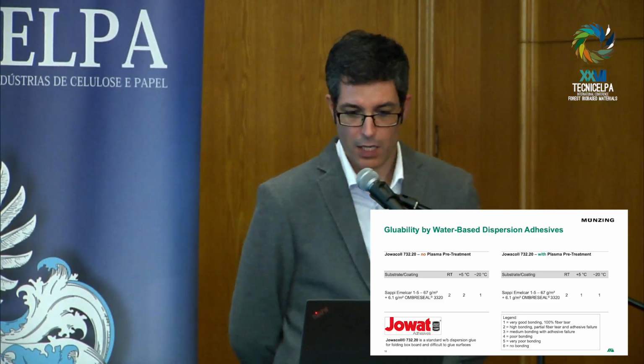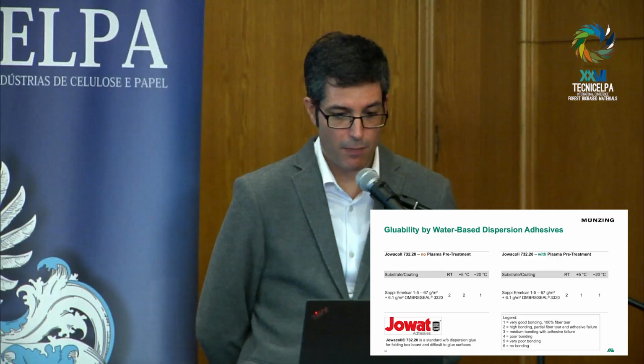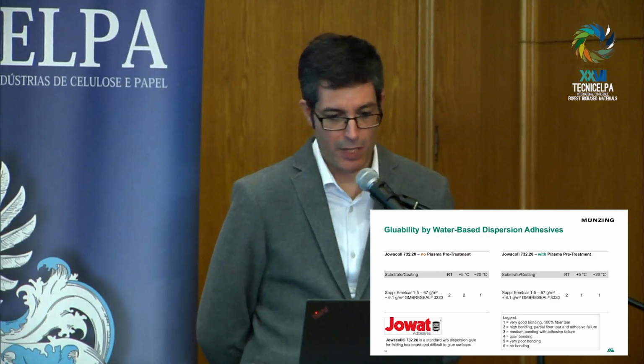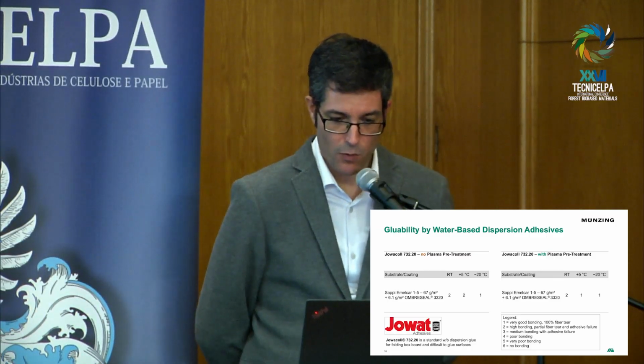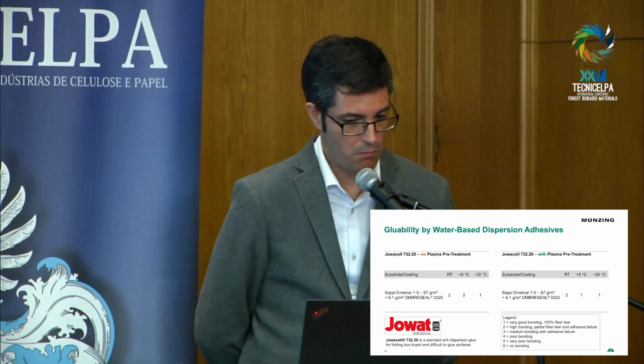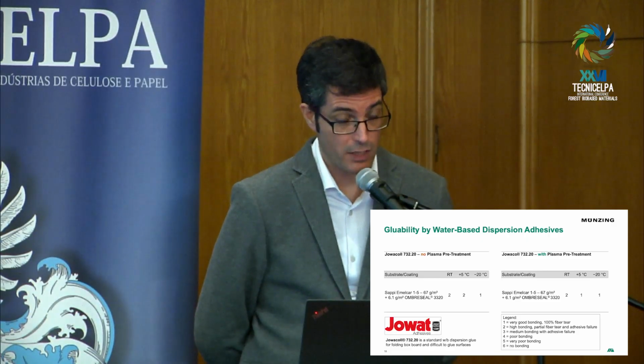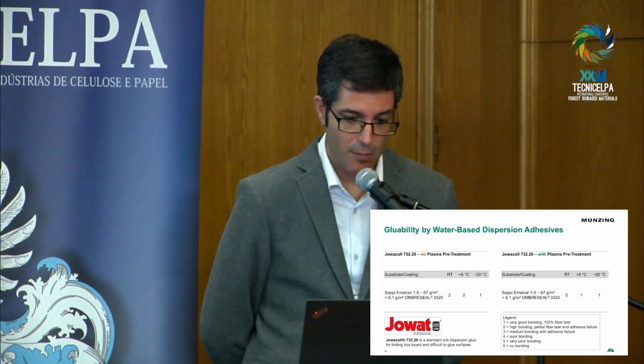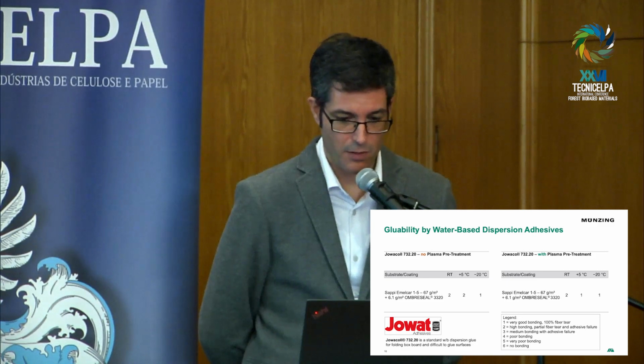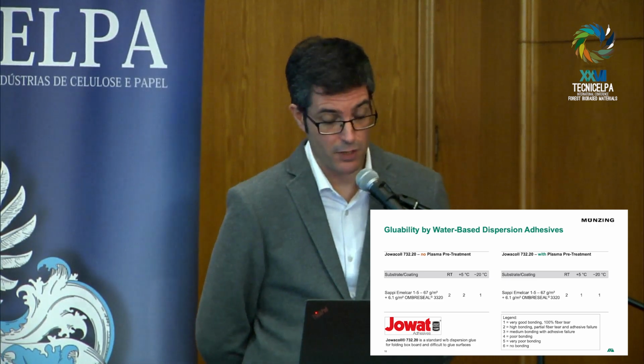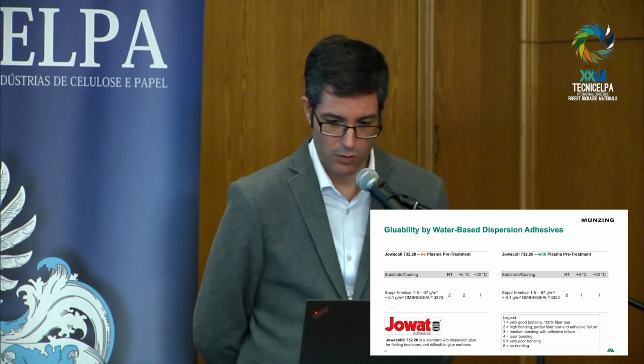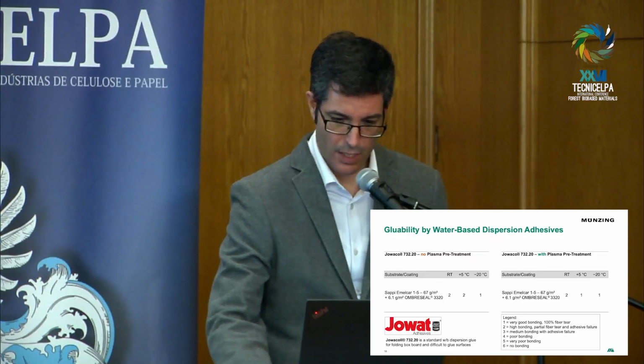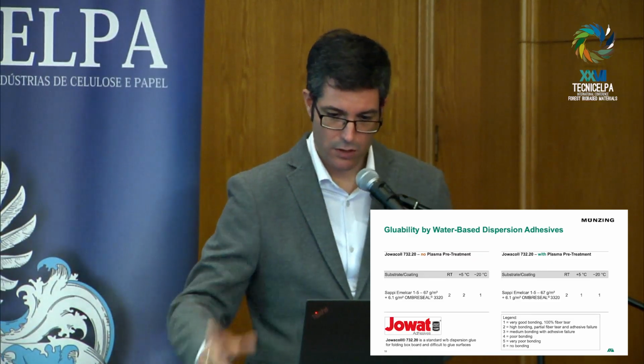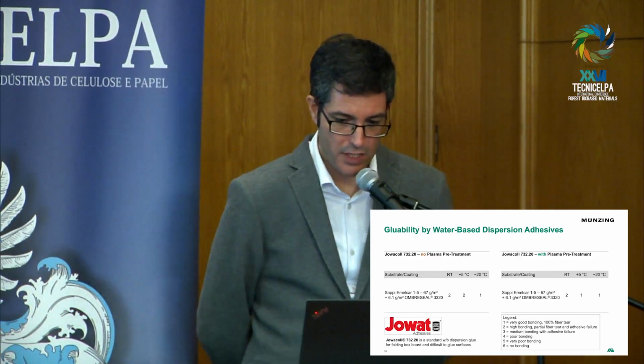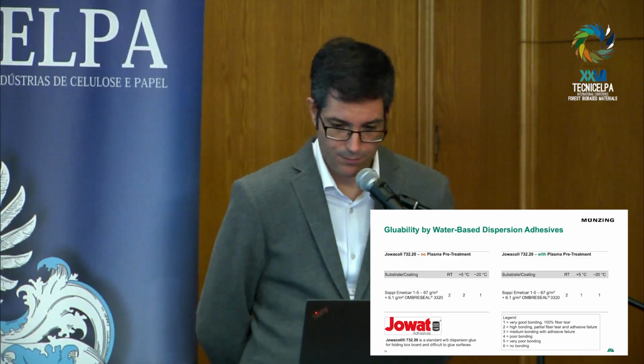When jumping to the pre-treatment with plasma substrate, we saw same result at -20, perfect bonding, also at 5 degrees, perfect bonding, and high bonding just with partial fiber tear and adhesive failure at room temperature, which is quite good result as well. For your information, the pressing time was 3 seconds with a steel roll.